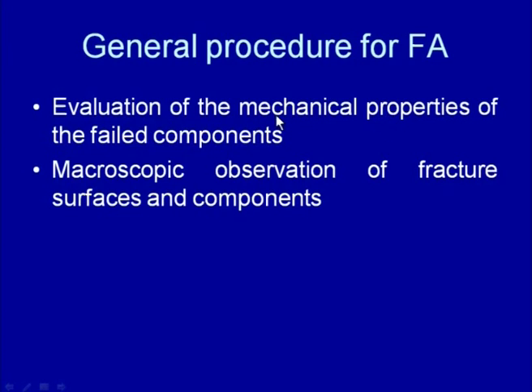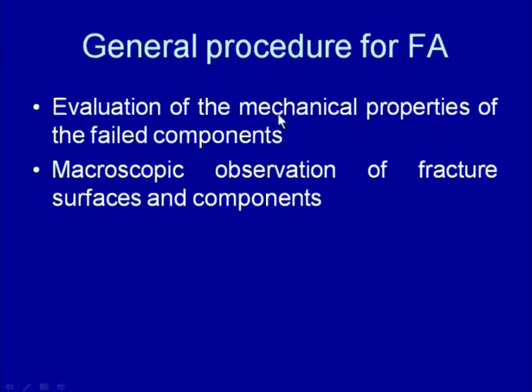If there is a deficiency in the mechanical properties of the material taken from the region close to the fracture surface, compared to the kind of properties it should have, then it will indicate that the material did not have the desired set of mechanical properties for successful performance under the service conditions to which it was exposed. So these mechanical properties of the failed samples are mainly used to see whether it was capable of performing under the service conditions or not.